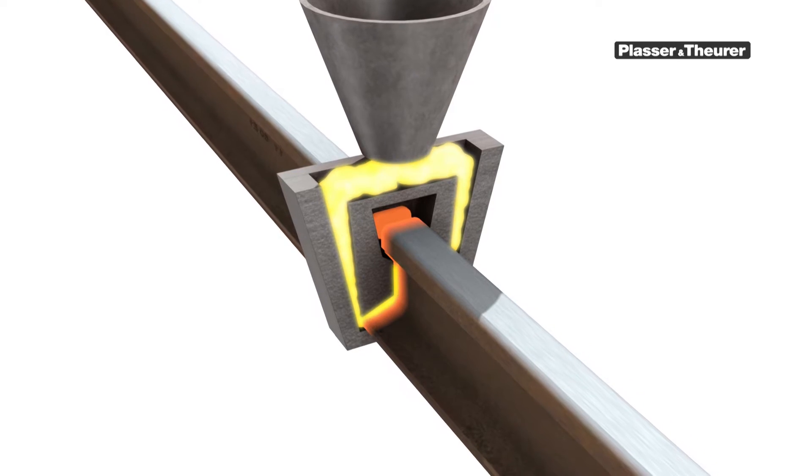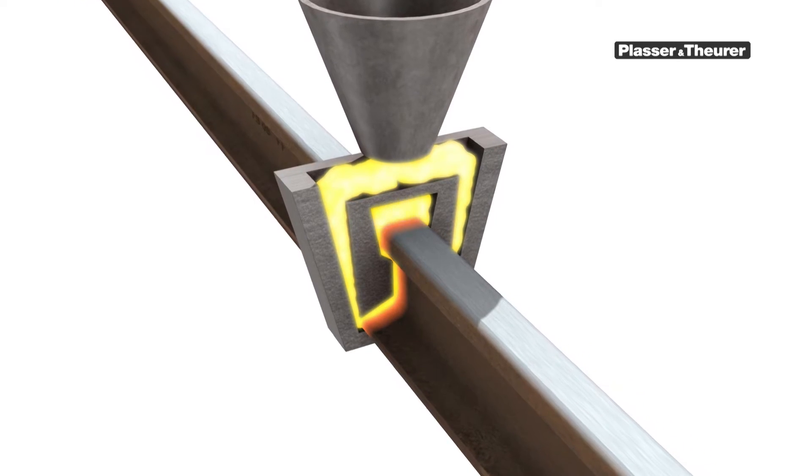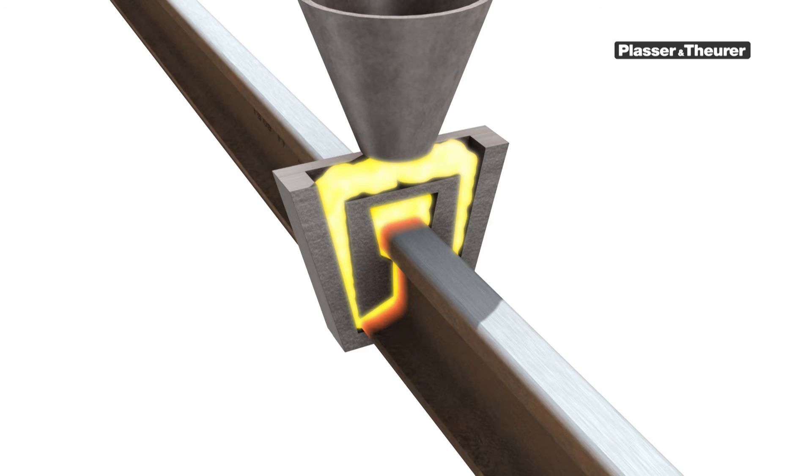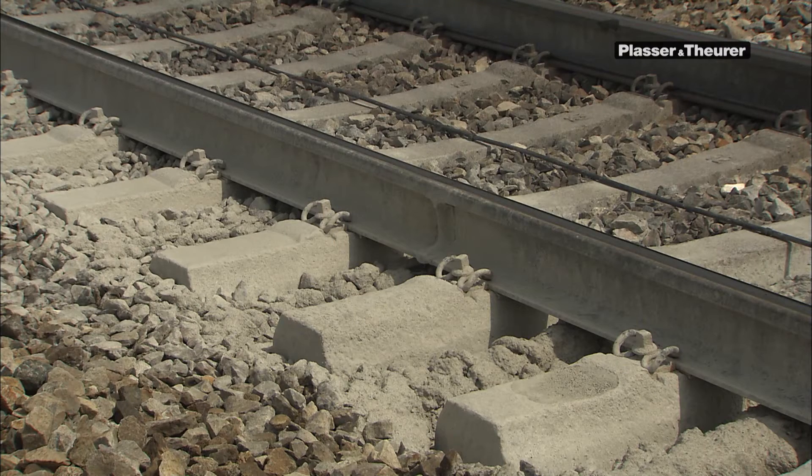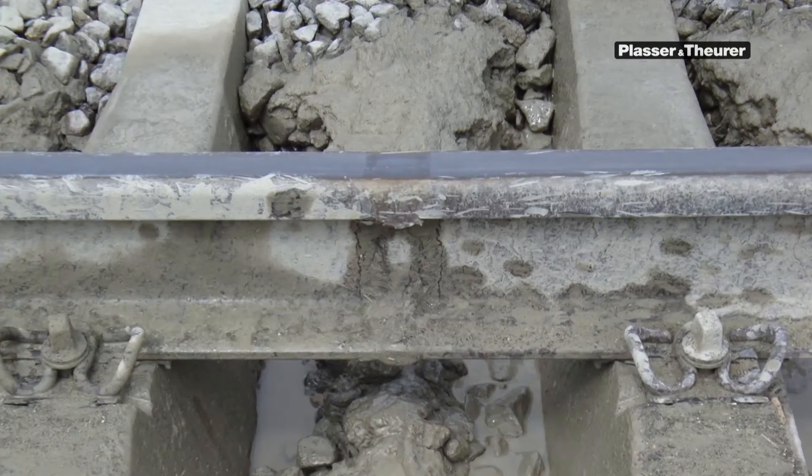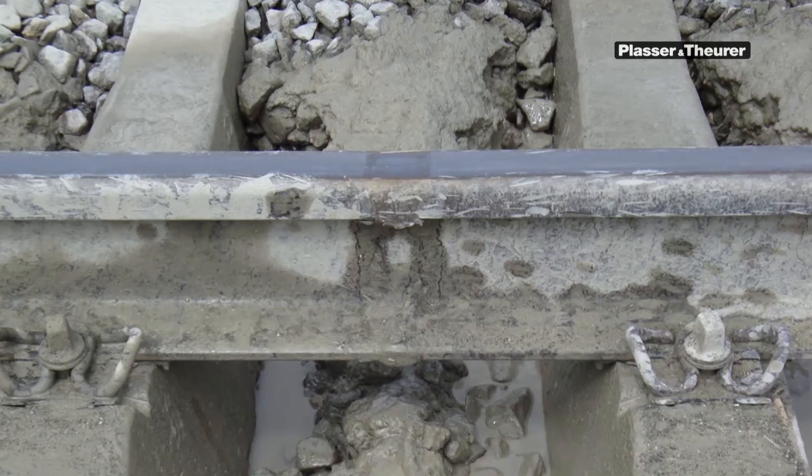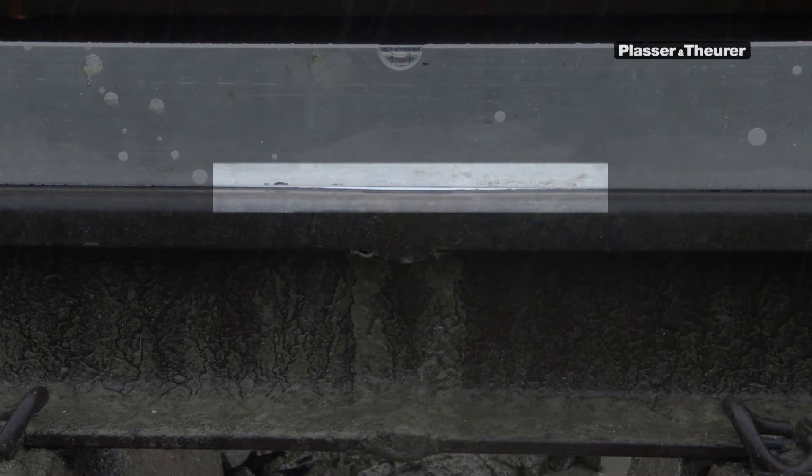The preparations are very elaborate and time consuming. The finished weld is inhomogeneous with a significant interruption in the hardness curve of the rail. This can lead to dipped welded joints, with negative consequences for the entire track at this spot. There is evidence that the breaking strength of such welded joints is lower than that of a flash butt weld.